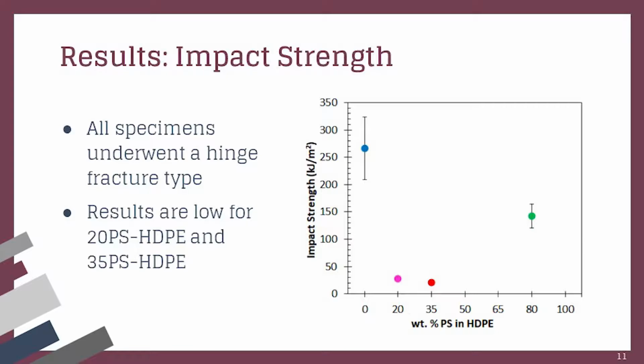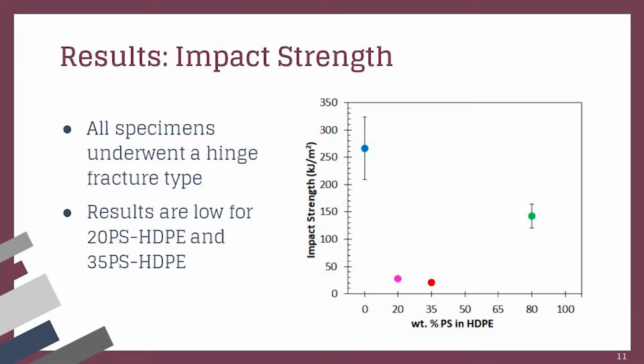So in our results, we noticed that all the specimens underwent a hinge fracture type. This is important because that just means that the piece itself didn't have a complete fracture. It still retained attachment. And as you see in our graph, we had two big outliers that didn't follow a downward trend, and further research needs to be done to really evaluate why this occurred, because it's known from prior research that the greater the polystyrene percentage in HDPE, the consistent lower trend there should be for the impact strength.